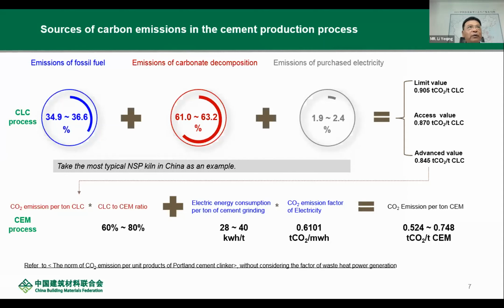Emissions from the fuel account for about 35%. This means about 300 to 315 kilograms per ton clinker. The third source is purchased electric power, which accounts for a small portion, 2 to 2.5%, about 16 to 21 kilograms per ton clinker. This is about the clinker aspect.